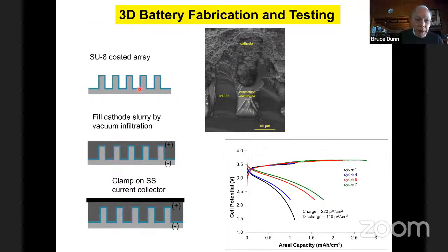So here's the coated array. We filled it with the cathode slurry, which in this case was lithium iron phosphate, put on a current collector and measured it. And indeed, this works. Now the charge and discharge characteristics are not the most beautiful, but you can see that you do get a couple of milliamp hours per square centimeter, not the design level, which is over 10, but that's okay. At least it's proof of concept of what you can do. And of course, you can run it for a few cycles.